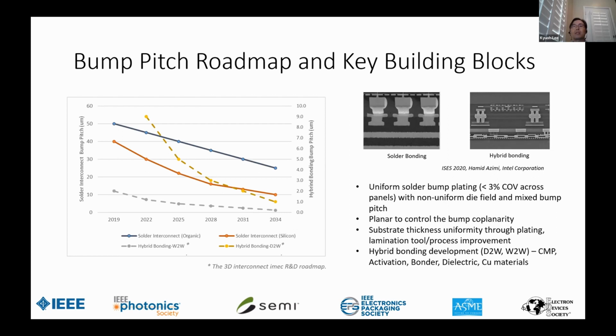There is a clear challenge in scaling the solder-based interconnect, mainly because of uncontrolled bulging and volume uniformity during the die bond, and that drives innovative solutions like hybrid bonding, a diffusion-based bonding. But in general, solder-based bonding has been well established in the industry for more than 10 years now. It's quite cost-effective, and the solder can act as some amount of buffer, absorbing the coplanarity variations coming from the die and the substrate.